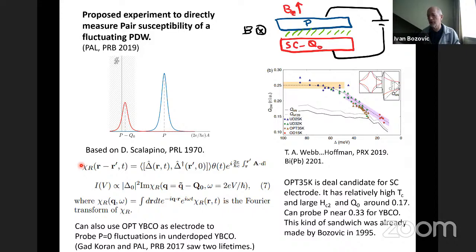So it has to either cross over somehow from one to another, or it has to have a phase transition in between. If we take Suchitra Sebastian's data, if you accept what you have just shown, then it is consistent with BEC, because the coherence length will be smaller than the average distance between the pairs. So there is no overlap between the pairs. So that's consistent with the BEC picture. Now the question is, what happens on the overdoped side? And that's where I have the problem, because if you look at the way that TC depends on the superfluid density and the way that superfluid density depends on the temperature, they are perfectly symmetric, underdoped to overdoped. So it, to me, looks like the physics is the same.